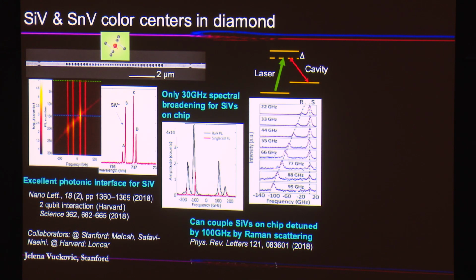So then we've also shown that we can compensate for up to 100 gigahertz of spectral broadening by Raman driving. And that's a pretty simple technique which people routinely use in atomic physics. So this is the energy level structure of the system. You just drive it with a laser, and you can detune your laser from the upper state transition. And as you change that detuning, you are also changing the frequency, the wavelength, of your Raman scattered photon into the cavity. And that experimental result is here, and we can change this detuning by up to 100 gigahertz.